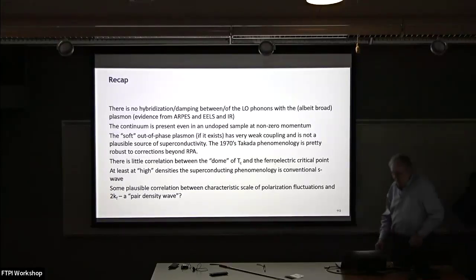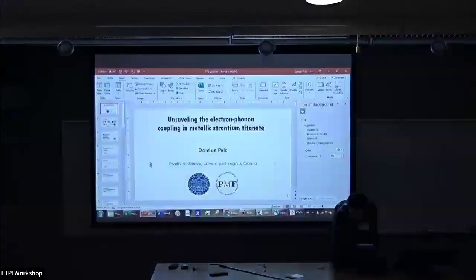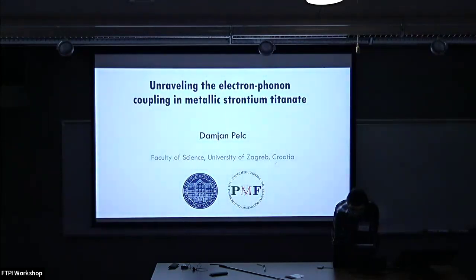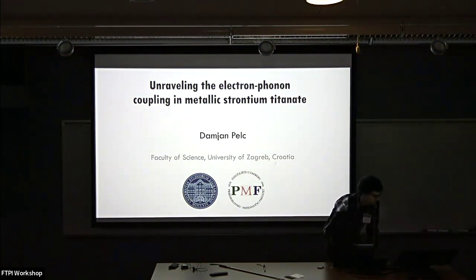One last question. So Peter, on the first part of the talk, there should be a phase transition to some sort of nematic or lamellar phase? Everything is a crossover. Why is that a crossover? Isn't that a broken symmetry state? Well, because the symmetry doesn't break. It's lamellar, but the lamella directions are fluctuating. Why are they fluctuating? Once you form the lamellae, it should be some sort of XY order parameter, so it should order. You're asking about the ordering within the lamellar phase, just the orientations.